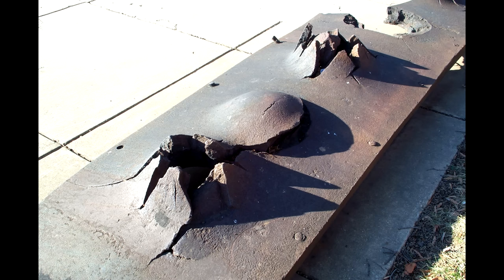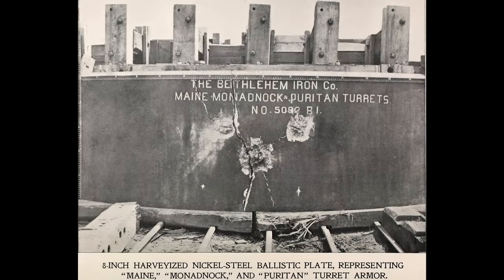Unfortunately, when iron-hulled ships then went to sea, they discovered that their plates were cracking quite a bit more than they had done in the tests, which was resulting in splinters, much larger entry wounds, which were obviously then much harder to patch up, and potentially the failure of entire plates.